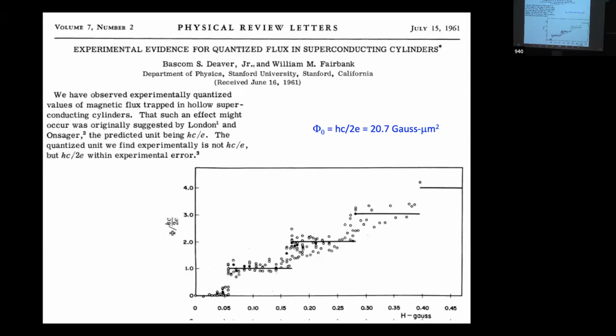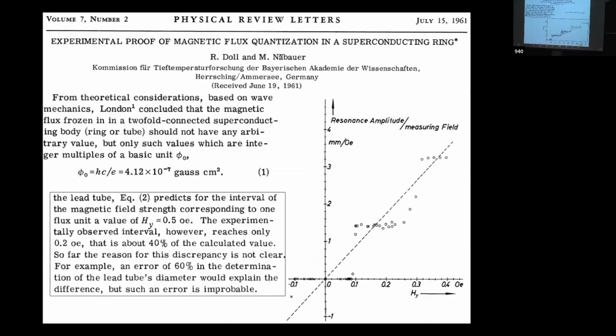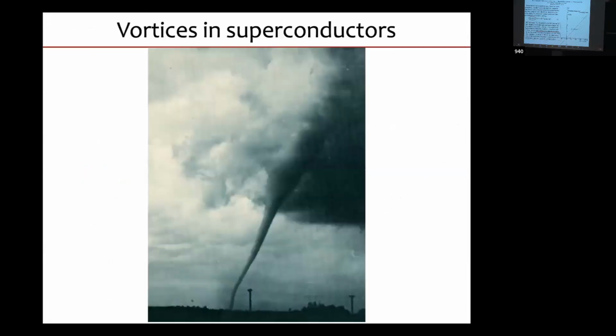So that's pretty cool. There was a more sober group of experimentalists that published in the same journal. And I would say their raw data was quite a bit better. But on the other hand, they were less bold. They basically said that the predicted unit was hc over e. The experimentally observed interval was 40% of the expected value. And the reason for this discrepancy is not clear. So they were very cautious and left it to the theorists to say, 2e, that's so cool, which is not something that I think most modern experimentalists would do, however cautious they are.